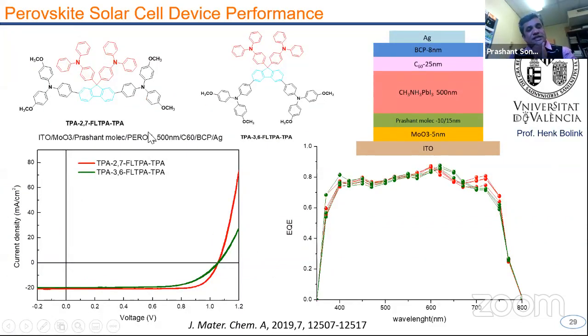Then we came up with another interesting molecule, which we can say is an emitter as well as a nice HTM. Here we took fluorene as a central building block and triphenylamine end capping groups. In this case, we put the methoxy-substituted triphenylamine at the 2 and 7 positions, whereas this triphenylamine is at the 9,9 position of the fluorene. And then we did the reverse structure where, instead of putting them at 2,7, we put them at 3,6. So these are some sort of geometrical isomers.